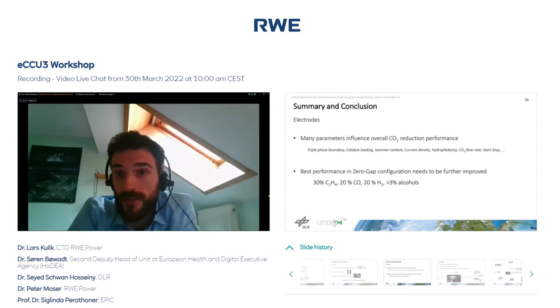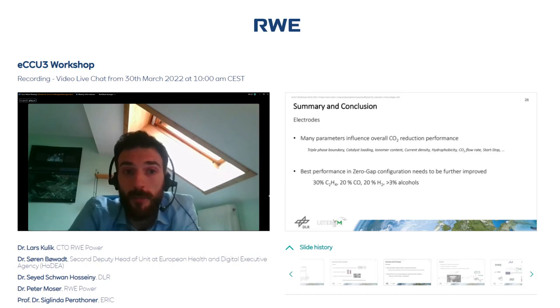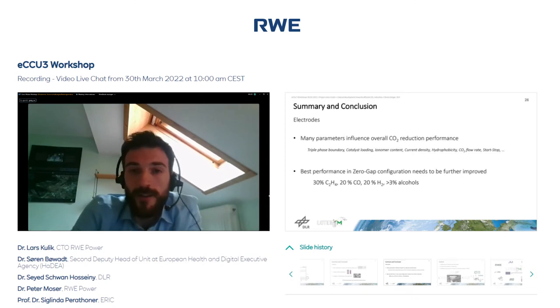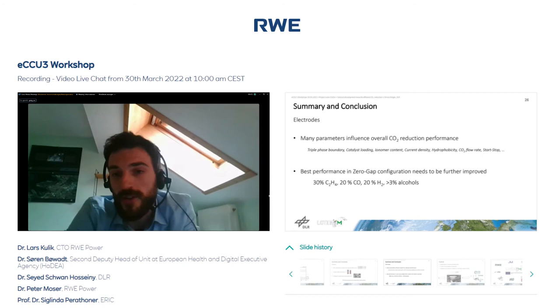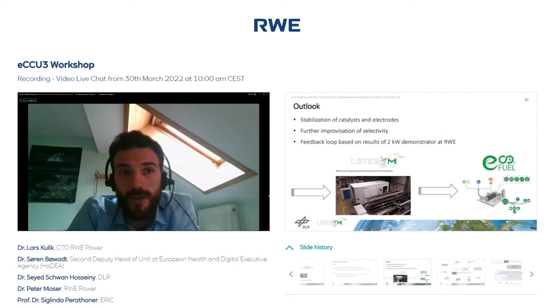And for the electrodes on slide 26, the summary would be that we have a significant amount of parameters that influence the performance that we all need to care about, and a bunch of them we have analyzed already, and our best performance in the zero gap configuration so far is written here with 30% ethylene and 20% CO. And this was also the result that is now the basis for the LOTER.CO2M demonstrator that has been already mentioned on slide 27. A short outlook is shown basically towards the LOTER.CO2M and also the eCO2Fuel project based on these results.